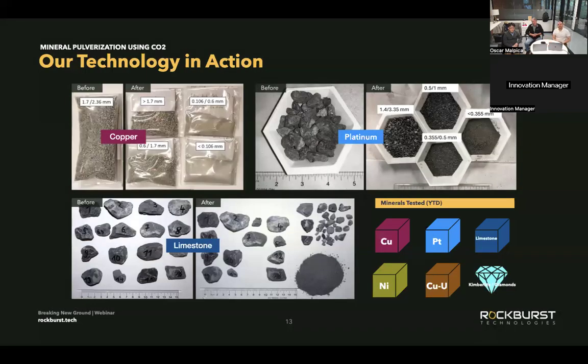Right. And this is an example of some feed and product that we've run through our tests in our prototypes. So on the top left, we have a commercial copper example with a bag of the feed ore size. It's 1.7, 2.36 millimeter, and then the bag products after running the tests on the right. And you can see significant amounts of fracture of the different size fractions there. We've run platinum through our process on the top right, and you can see the feed size before, relatively large size. And then again, we've got reduced size fractions that come out of the comminution process.